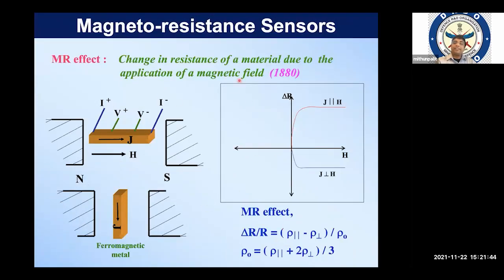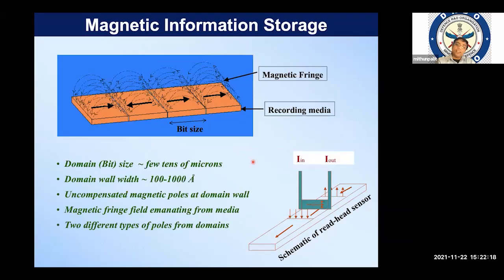The other important magnetic sensor material is the magnetoresistance sensor. This material has particular properties. You keep it in the direction of the field, flow a current and measure the resistance, and then you make the material perpendicular, flow a current, and measure the resistance, and you will see there is a change in the resistance. This resistance change is called magnetoresistance, and it can be used for sensor application, and also for magnetic information storage, because you can change the orientation of the magnetic domain by applying an electric current from outside and then measuring the resistance, so you can read it as 1 or 0.